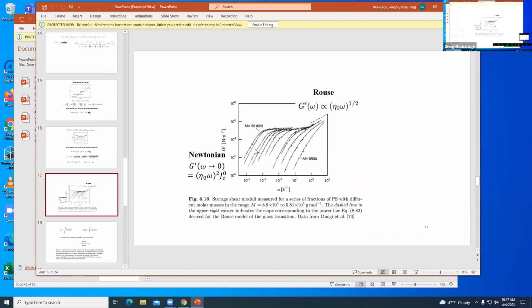So that's why in the flow part you get this power 2 for the G prime. Then you reach a point where you see a plateau where it's a rubber, because on the time scale the entanglements can't relax. You get rubber. Then you see Rouse behavior at the high end, at the high frequency where you look within the entanglements, and the thing just flows there. I mean, it flows like a Rouse fluid. It's like a spring controlled viscous element thing.